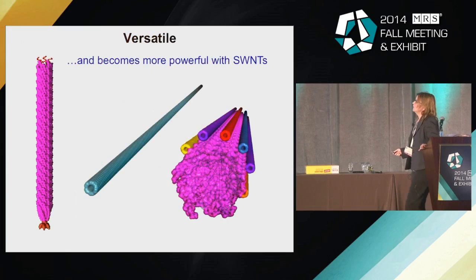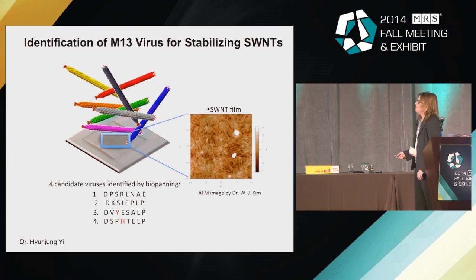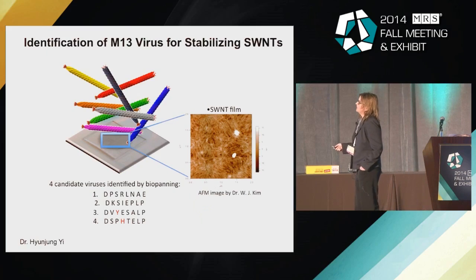And so we engineered this virus to now pick up single-wall carbon nanotubes and line them around the surface of the virus. You can put 1 carbon nanotube on a virus, or you can put up to 10 carbon nanotubes on the virus, and they're each held in place by about 200 peptides that are specific to bind these carbon nanotubes. And these were found by taking a library of these bacteriophages and interacting them with carbon nanotube film and finding the one that would bind the best.